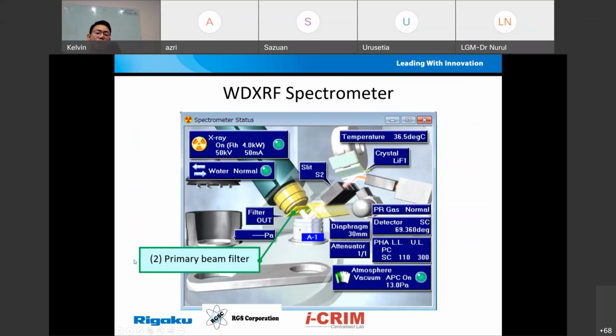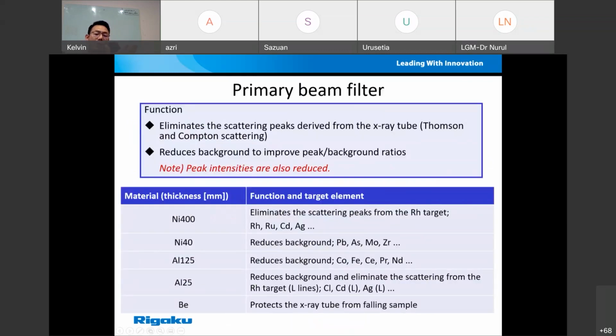The second part is the primary filter. The primary filter removes the background and also improves the measurement capacity. Another very important part for the tube below system is to prevent debris from the sample from dropping onto the tube itself. In the tube above system, this is not important because it is quite impossible for the sample to drop onto the detector crystal or the X-ray tube. But for the tube below system, when the sample drops onto the tube, it might damage the tube. Subsequently, it is a very high cost to replace the tube.